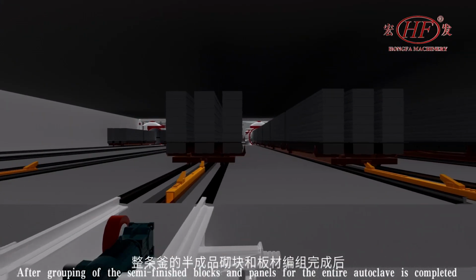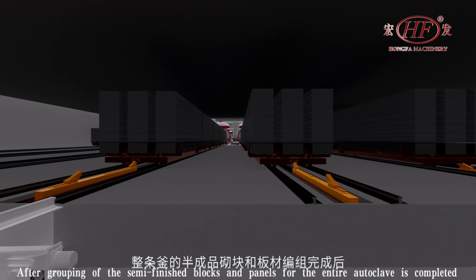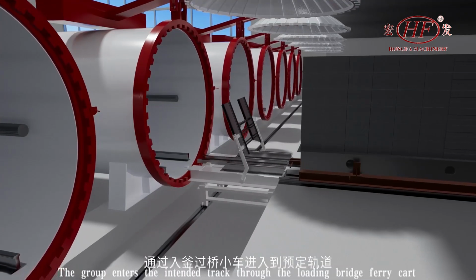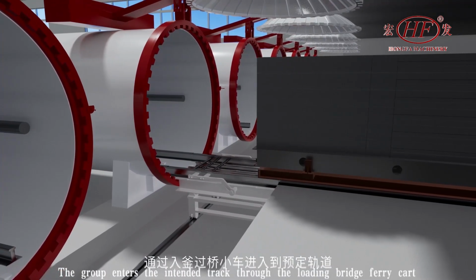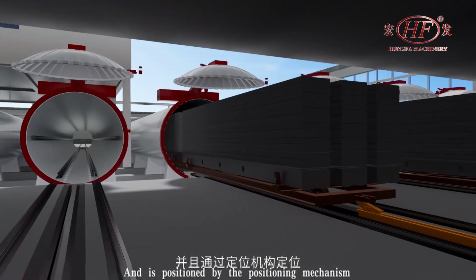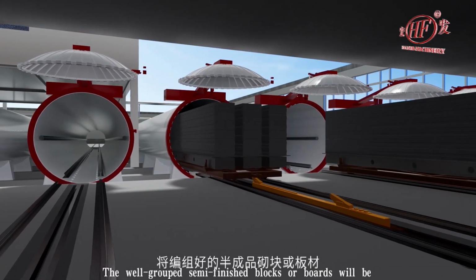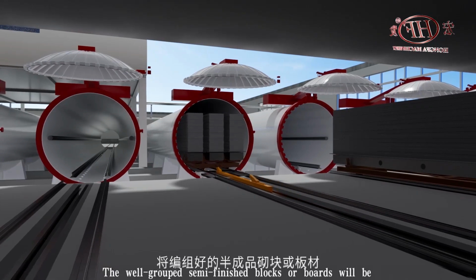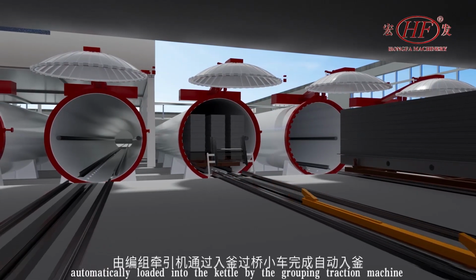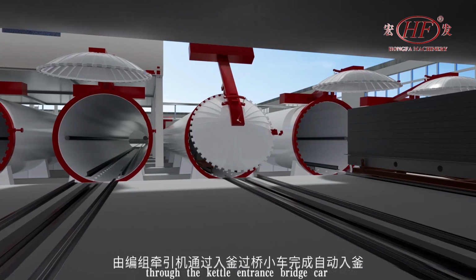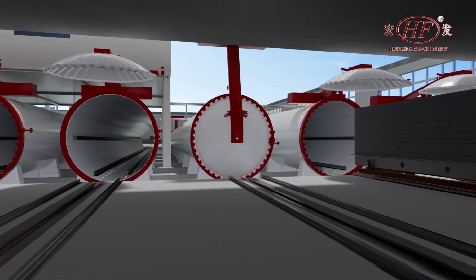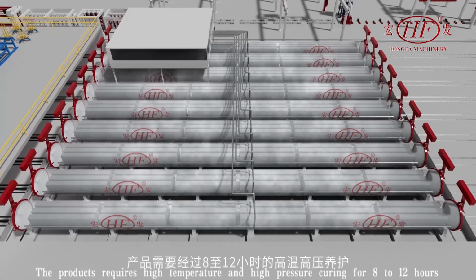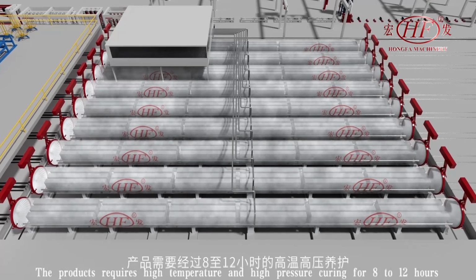After grouping of the semi-finished blocks and panels for the entire autoclave is completed, the group enters the intended track through the loading bridge ferry cart, and it is positioned by the positioning mechanism. The well-grouped semi-finished blocks or panels are automatically loaded into the autoclave by the grouping traction machine through the loading bridge ferry cart. The products require high temperature and high pressure curing for 8 to 12 hours.